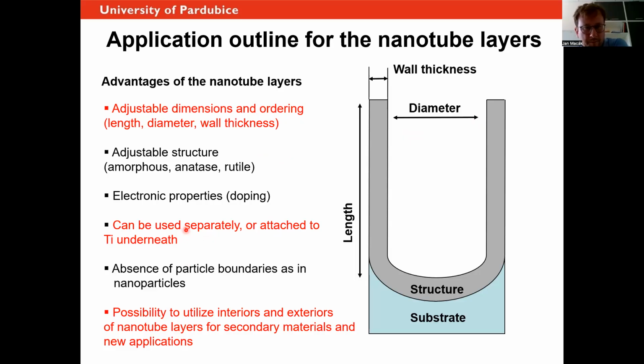And what is also important is that these tubes are normally very well adhering to the substrate, the titanium underneath. But there are tricks how to separate it. So actually you can make really freestanding nanotube layers or membranes or whatever. And this can be very handy for some applications.